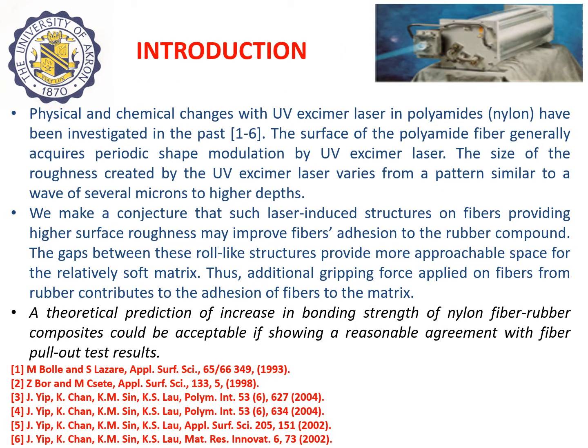Physical and chemical changes with UV excimer laser in polyamides or nylons have been investigated in the past. The surface of the polyamide fiber generally acquires periodic shape modulation by UV excimer laser. The size of the roughness created by the UV excimer laser varies from a pattern similar to a wave of several microns to higher depths.